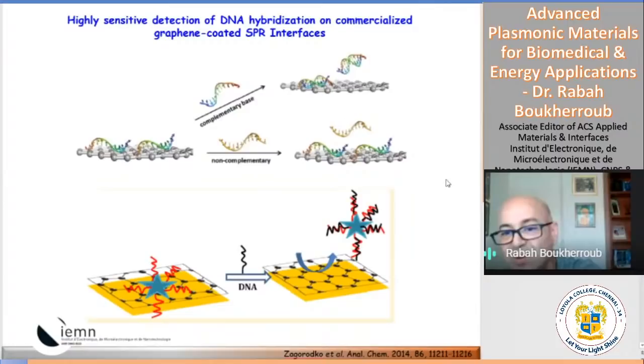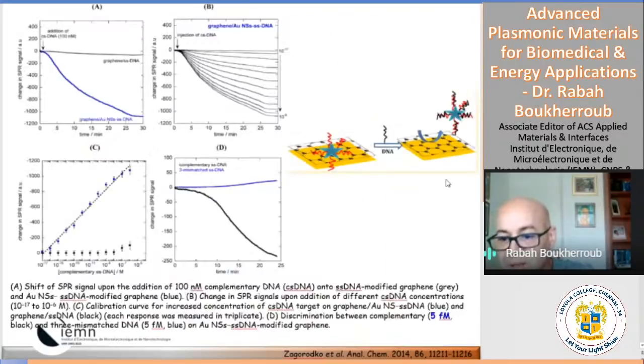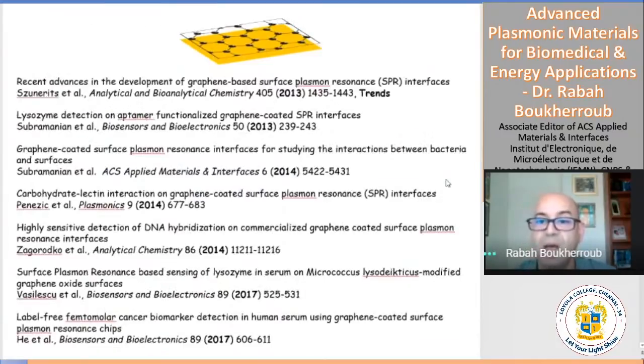You know, the hybridization has an energy input which is much higher than the interaction of the simple graphene sheet with the DNA, and this goes off the surface. So we can really do that very nicely. And if you do non-complementary, of course, it's not the same. It doesn't work the same way. So we used this concept, and we could detect DNA hybridization with a very nice sensitivity, below 5 femtomolar. And of course, we extended to different functionalization schemes and different applications to sense bacteria, but also to study bacteria, sugar or lectin interactions, and also different types of biomarker detection using this technique.